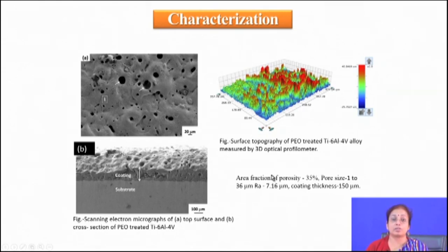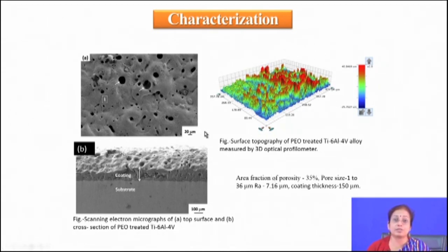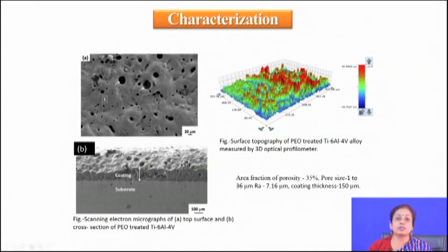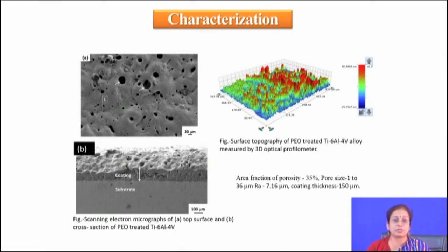This is a case of micro arc oxidation on titanium Ti-6-4 substrate. On the surface there are many porosities, and if you see the cross-section there are also porosities. However, an interesting finding from this research investigation is that these porosities are not really interconnected. Even though there are porosities on the surface, they are not connected to each other.